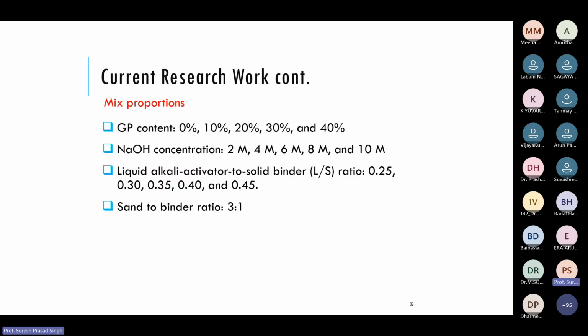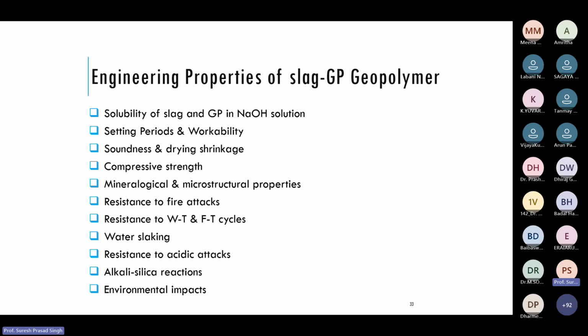So we have tried different GP contents, with sodium hydroxide concentration from 2 molar to 10 molar, and liquid alkali activator to solid binder ratio from 0.25 to 0.45. And we prepared these mortar samples with standard sand and binder ratio of 3:1. Time will not permit me to go through all these things, so I will just tell you the salient features. The solubility of slag is the basic thing you have to see, the release of silicon and aluminum ions.